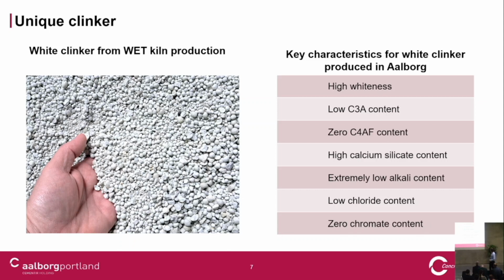We have a very high content of calcium silicate. That is the mineral giving strength to the cement. Because we have no C4AF and very little C3A, only what is left is calcium silicate. So that's why we can have much higher silicate content than in a normal grey clinker.